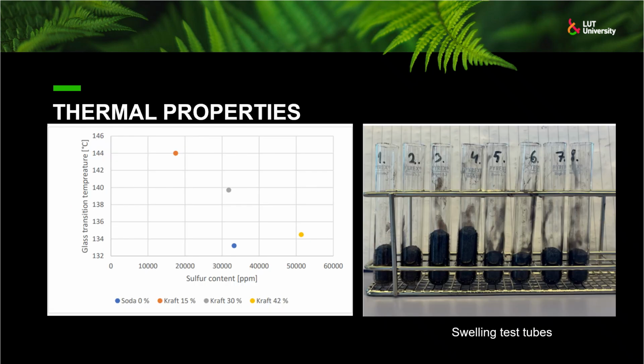Thermal properties. Two different thermal properties, glass transition temperature (Tg) and swelling, were measured from lignins. Based on the internal database, the measured Tg values were lower than typical softwood kraft lignins, which usually range from 140 to 160 degrees Celsius. Soda lignin had the lowest glass transition temperature. As a general observation, an increase in sulfidity led to a lower glass transition temperature. A strong correlation was found between sulfur content and Tg in kraft lignins. However, soda lignin was not in line with kraft lignins.